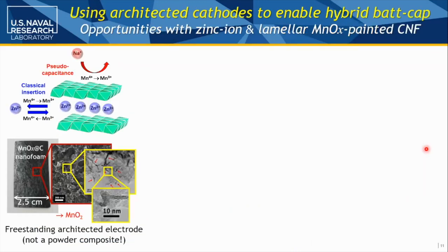But there's other things you can do with birnessite. So maybe 6-7 years ago, people said, well, why don't I take out those boring sodiums or potassiums between the layers and have divalent zinc in there, the start of the zinc ion battery. So you're in a mild electrolyte, often a zinc sulfate aqueous system versus zinc foil. And you're going to try to charge and discharge that birnessite. So we're coming in with our birnessite on carbon nanofoam, not the powder composite almost everybody else in the world studies.